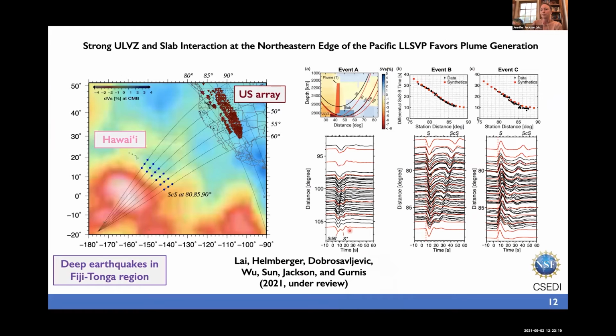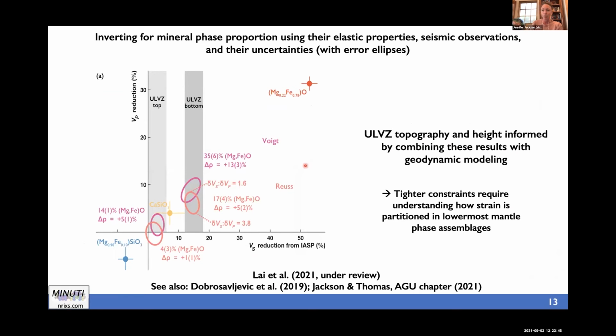Going into some of the details of how one could get a little bit more quantitative about this interpretation is working together with Don Helmberger and graduate student Vun Lai and Vasily Dobrosavlevic. We did look at this region underneath Hawaii and performed an inversion using the mineral phase proportions and their elastic properties, the seismic observations, and their relative uncertainties to compute the elastic properties of the phase assemblages and invert for what proportion of this iron-rich magnesiowüstite could explain the seismic observations, which point to a very slow basal layer and a relatively, still slow, but just a low velocity region near the top.